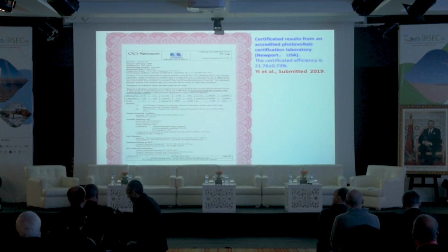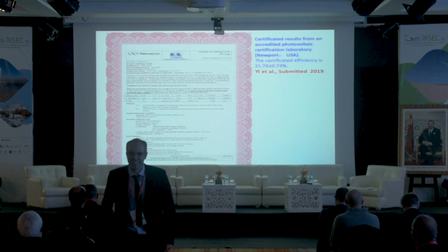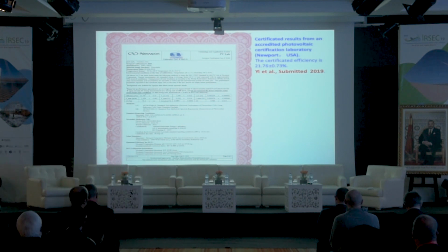That was measured in our lab, and these cells were sent to Newport in February, where they measured 21.8 plus or minus 0.7, showing that our laboratory measurements and our system are consistent with international laboratories. So this is a certified efficiency which we got from Newport, 21.76 plus or minus 0.7.